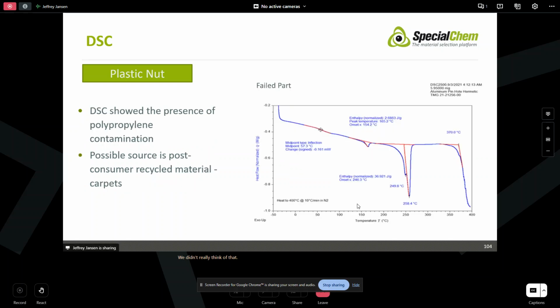We measured moisture content, but the suspected parts were high in moisture, so we got a softening effect through the plasticizer. But again, not a consistent trend. We didn't really think that was going to tell the full story.